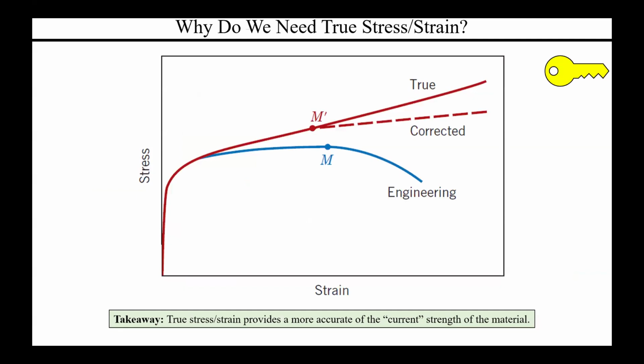So that leads us to this. So we have three curves here: engineering, which is what we've already talked about; true, which is the new value; and this corrected. So what you'll see again is that all three of these are effectively the same within the elastic region. That's because the cross-section area is not really changing with respect to the initial conditions. And even once you enter into that plastic region, that non-linear region, there's still a significant period of time where that area is not really changing that much. So the engineering and true values are going to be very similar.